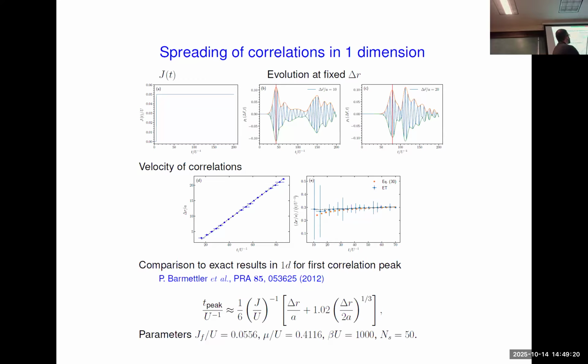We fit the envelope of this single particle density matrix and use that to extract the center of the wave packet, and you can plot that position as a function of time. There are exact results for the peak at a given R or delta R that were obtained in the strong coupling limit by Barmettler et al., which are the orange dots here, and you can see that numerical results agree pretty nicely with those exact expressions.